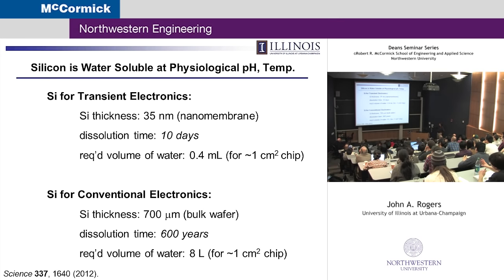So silicon at a thickness of 35 nanometers, we know how to do that pretty well. Dissolution time, physiological pH and temperature, 10 days. It only requires 4/10 of a milliliter of water for a chip that's a centimeter squared on a side. So a very small amount of water is required.